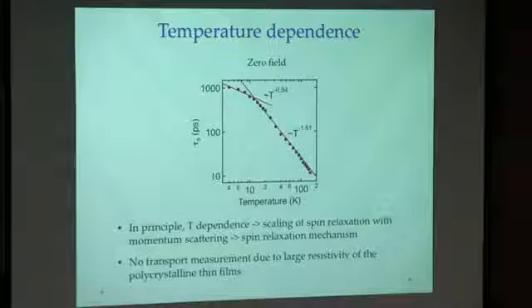Further, I would like to discuss the spin relaxation mechanisms, so we did the temperature dependence of the spin dynamics measurement. This is the spin lifetime as a function of temperature in a log-log plot. And we can see that it shows two regimes. For the high temperature, above 15 Kelvin up to 150 Kelvin, we see a power law dependence of T to the minus 1.5, roughly. In principle, the temperature dependence tells us the scaling of spin relaxation with momentum scattering. And that should give us some clue on the spin relaxation mechanisms.